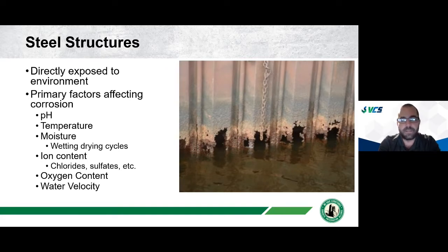Water velocity is another important factor with regards to corrosion in marine structures. So if you have really fast tidal swings that can cause a lot of water motion, that will wash away the buildup of iron oxide on the steel structure and allow it to corrode more rapidly. Also, when we're talking about port structures and berthing elements, where the bow thrusters or the propellers are, that water flow can cause more localized corrosion in those areas.